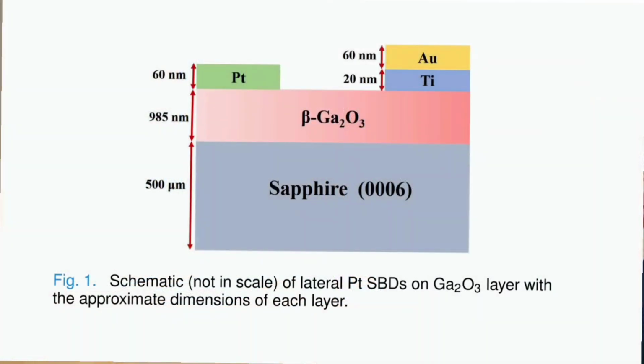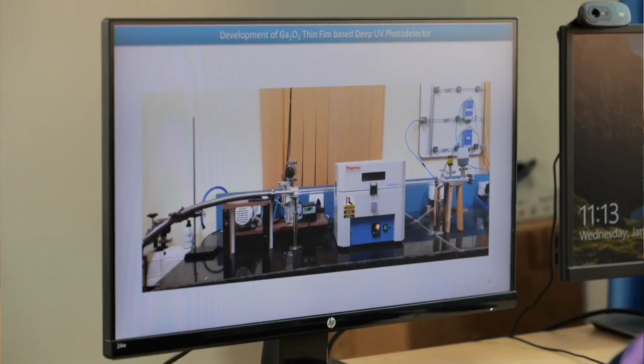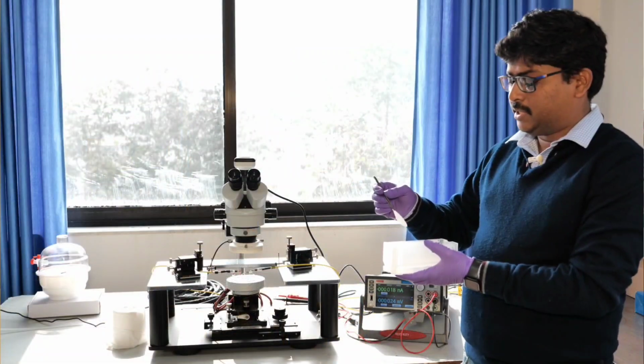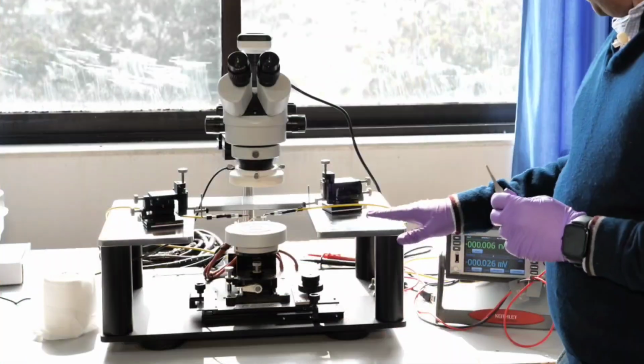The primary challenge in this recent research development was to develop this new wide bandgap semiconductor, gallium oxide. This is another compound semiconductor where both gallium and oxygen atoms are present. For the material development technique, we used a low pressure chemical vapor deposition setup, which is not a typically very costly system. We developed this system on our own, and it is completely customized.